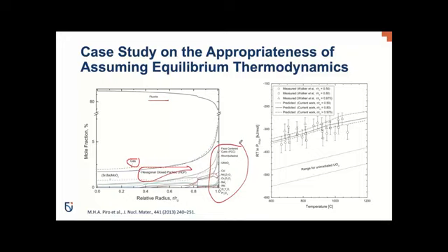But what's also worth noting is that the same predictions agree fairly well with other experimentally measured values, such as the relative oxygen potential in the fuel, as shown on the right figure from the same set of predictions with measurements performed at JRC. And ultimately, what's worth noting is that the error bars are still pretty large, and that's no criticism of the experiments. It's just, irradiated fuel is incredibly complicated. So here's an example of where assuming equilibrium may not be that bad, but at least here we have some experiments to bound our levels of expectations.